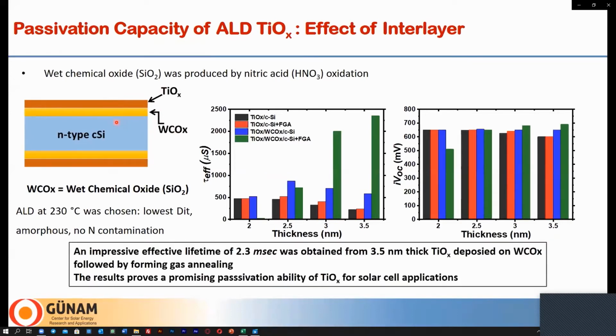As you see here, we have reached a very high effective lifetime, exceeding 2 milliseconds, which is quite successful. This is obtained with 3.5 nanometer thick titanium dioxide deposited on the chemically grown oxide, followed by forming gas annealing. This high lifetime translated to a VOC of more than 700 millivolts. So this result proves a promising passivation ability of titanium dioxide for solar cell application.